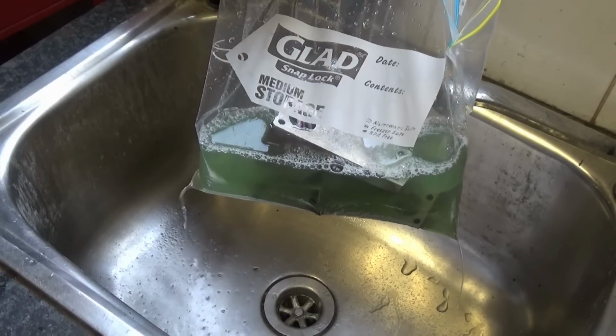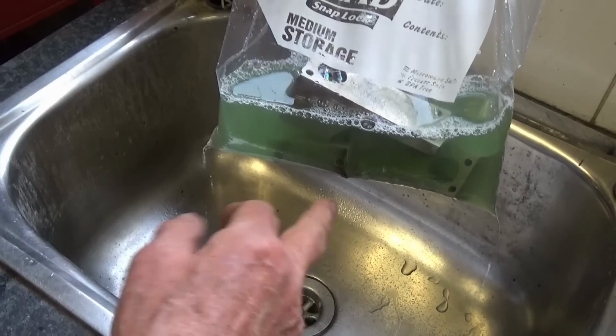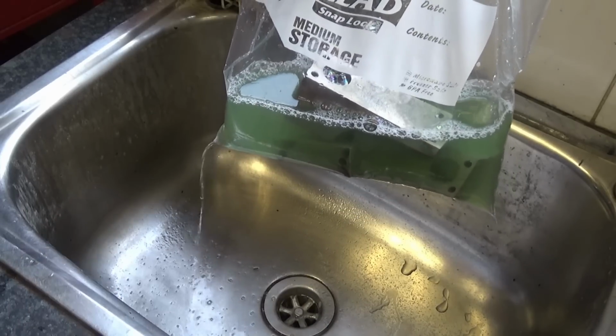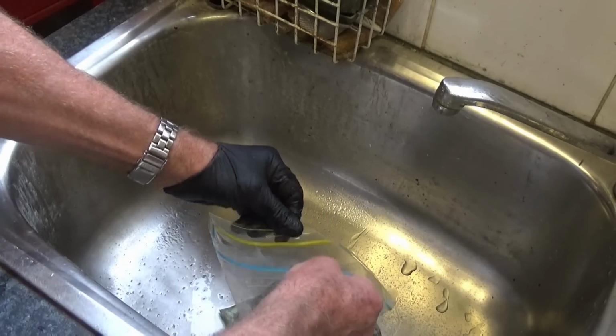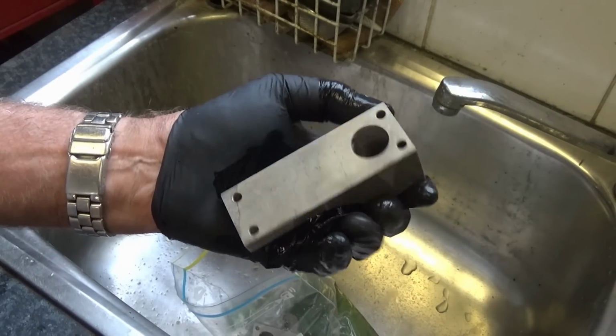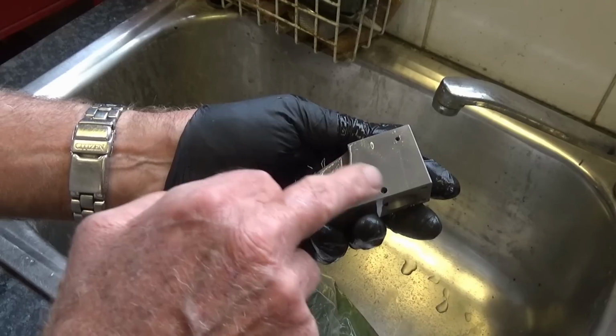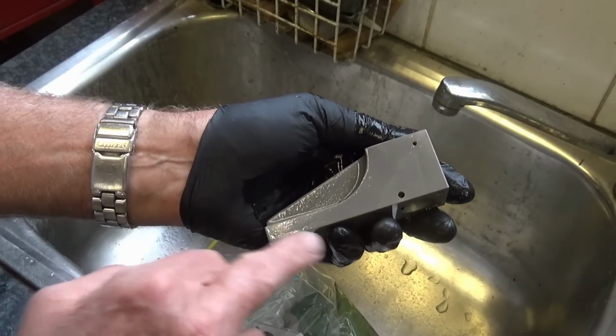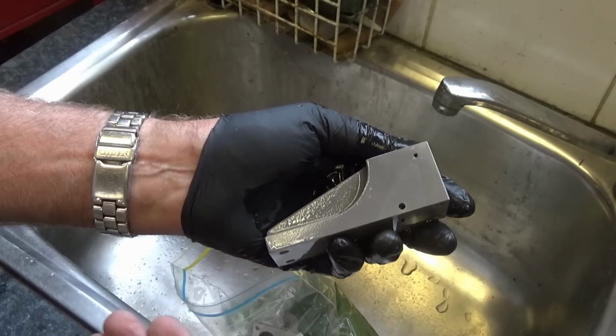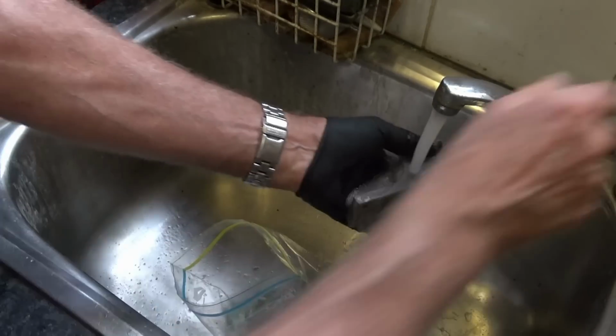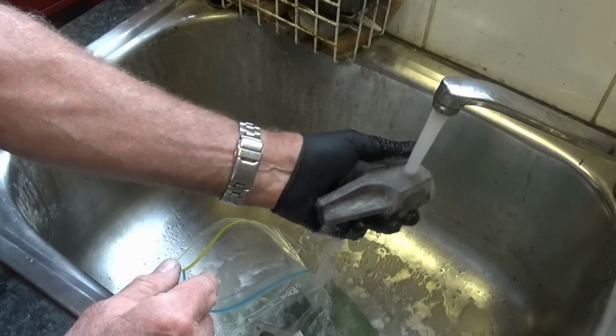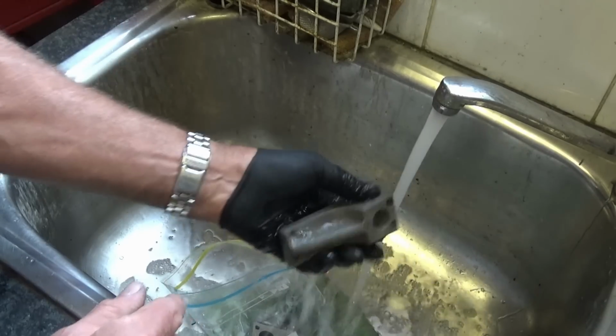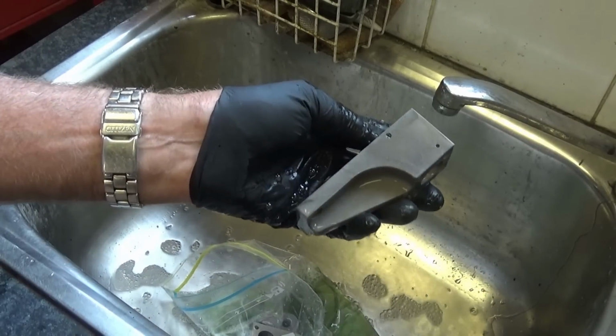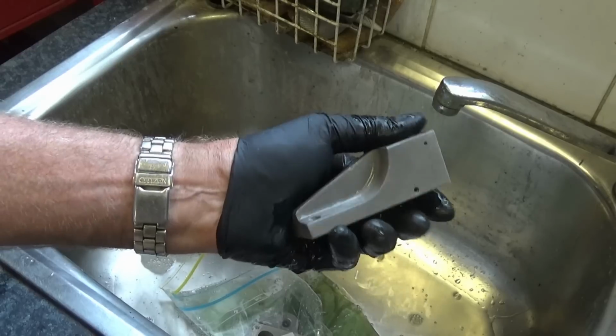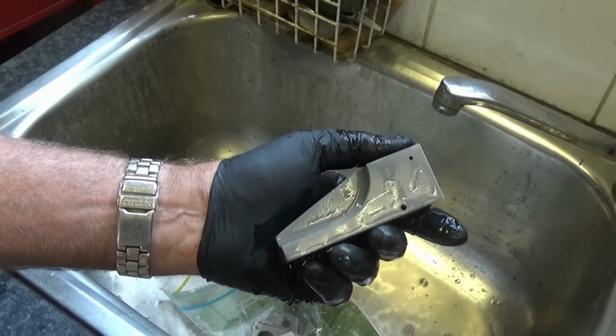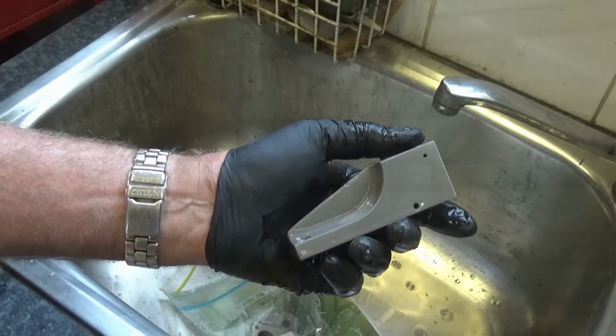So this is the bag that came out of the ultrasonic cleaner. You can tell by the colour of that cleaning fluid that there's a lot of contaminants in there. I think this is the one that had the porosity on the surface, but I'll rinse this one off. If there's any water breaks on the surface there, it means that there's still oil coming out of that material. That looks slick all over, so I think we've got rid of the oil, but I'll put this back in the oven to dry it off and then we'll powder coat it.